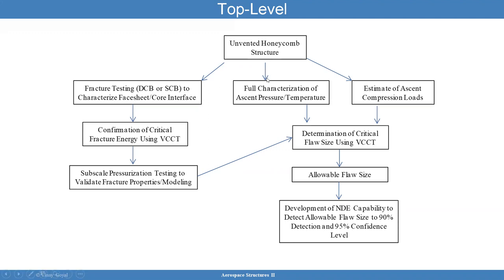You want to fully characterize the ascent and pressure environment and the compression loading environment for the aircraft, spacecraft, or launch vehicle. With these loading conditions, you can determine the critical flaw size that can cause failure using the virtual crack closure technique — a technique to predict failure in a composite structure. You can use that to determine the allowable flaw size, and then make sure your design can inspect for this allowable flaw size.